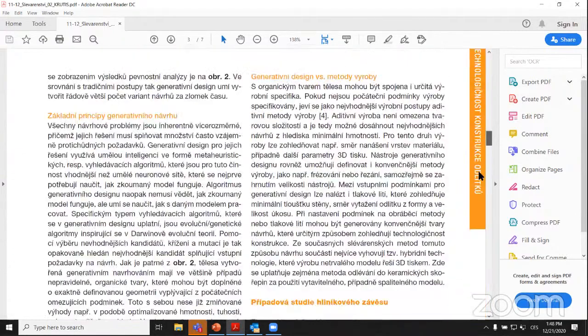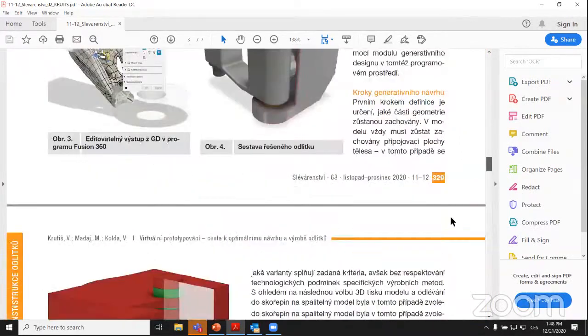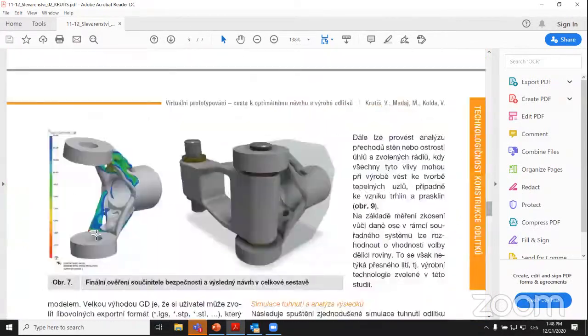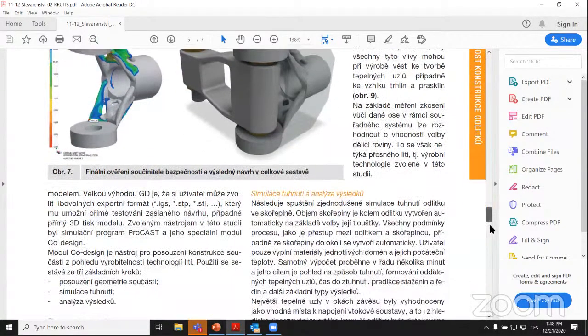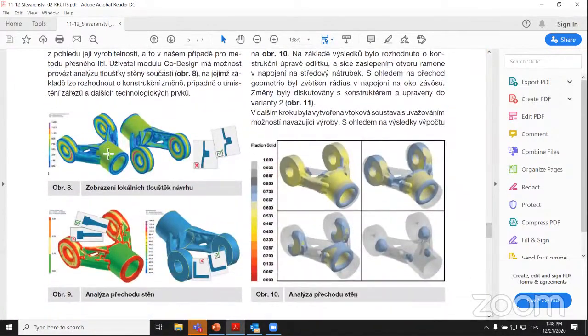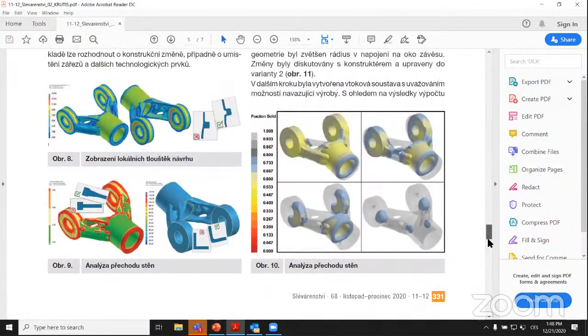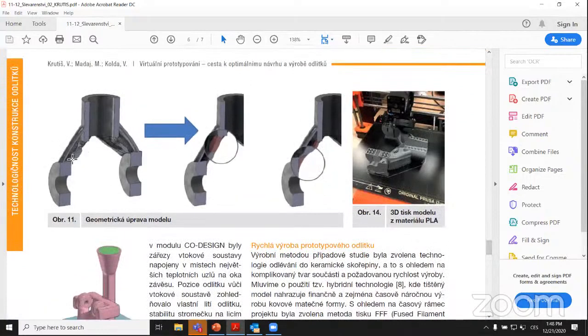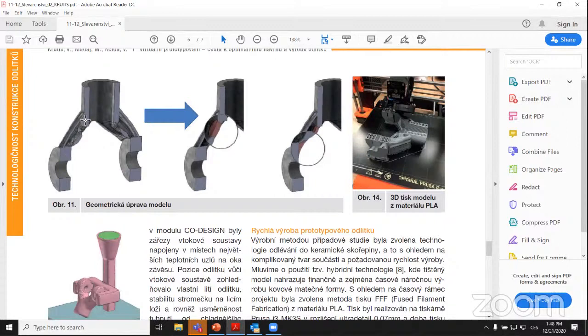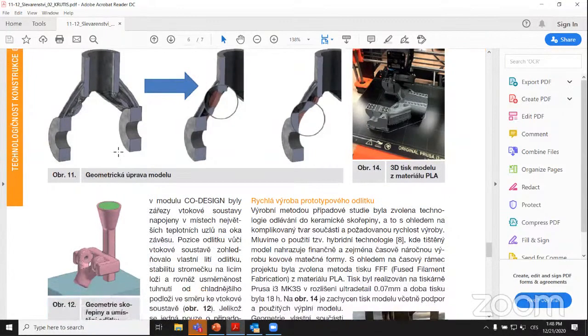Based on this, we choose. This is some outcome of the software. Based on this, we choose some design which was, from the castability point of view, most okay, I would say. Then we go through these geometrical checks and the simple solidification simulation. And based on the result of this simulation, the design of the part was changed a little bit. You can see some additional material added here and here, simply to let the solidification go as expected.